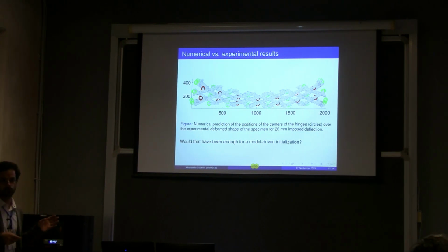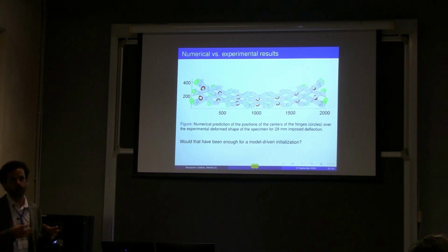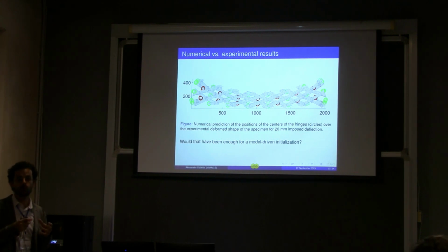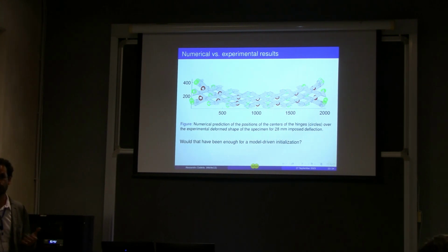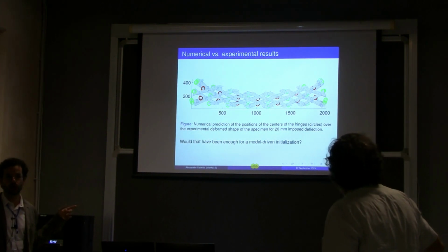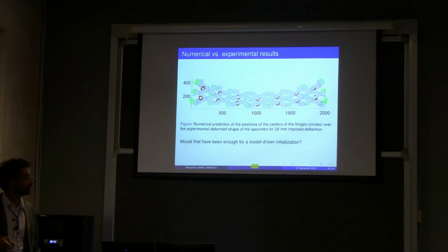Now, the agreement is not perfect, and we have several reasons for this, because we have a very non-dense specimen. The specimen is full of gaps that clearly introduce errors compared to the numerical simulations, but a posteriori I would say this is a good first guess for the DVC. It is sufficient for avoiding the nightmare we had doing everything manually.